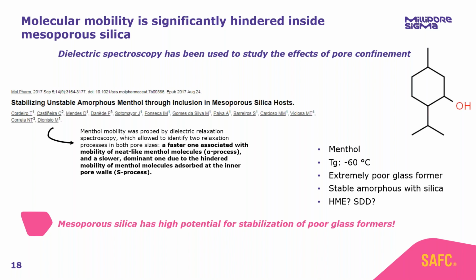And so it was remarkable that this team observed that menthol was able to be stabilized in the amorphous form at room temperature for 12 months. So mesoporous silica was successful in stabilizing this extremely poor glass former. And this clearly would not be possible with hot melt extrusion or spray dried dispersion.